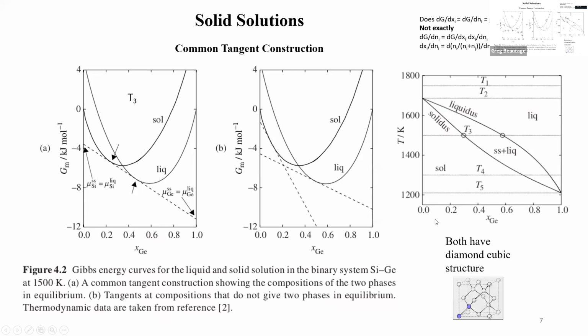So this is a solid solution, so this is silicon germanium, and they're both diamond cubic. And they're about the same size, just one step away from each other in size. They can make a diamond cubic crystal all the way across from 0 to 1, randomly mixed germanium in the silicon. So it's just one crystal, and if you heat it up, it melts into one liquid with the same composition. But if you're in the gap between these two at T3, then it's going to separate into a solid and a liquid of two compositions. One's mostly germanium liquid, and one's mostly silicon solid. So you have a solid and a liquid in equilibrium with each other in this region.